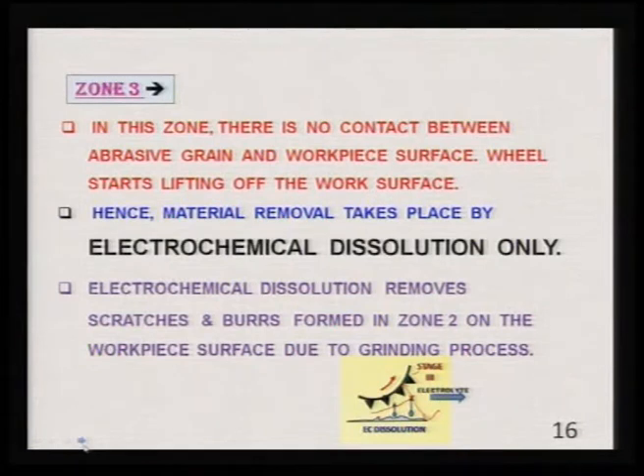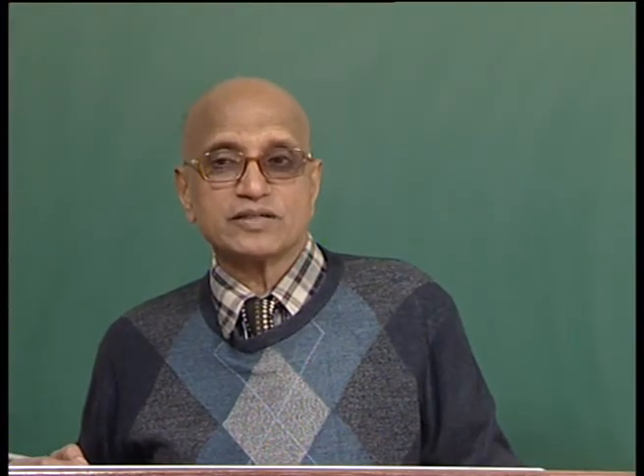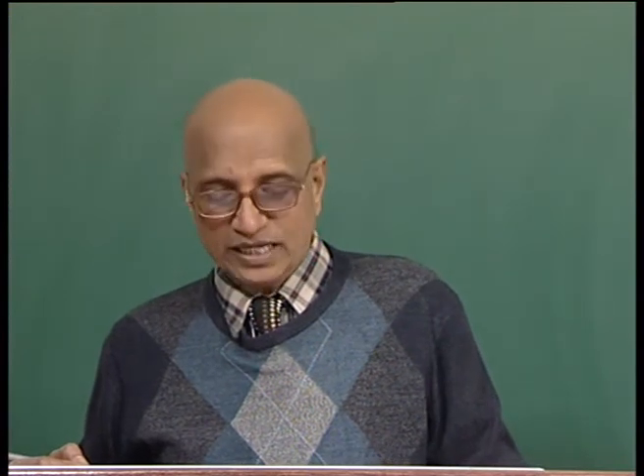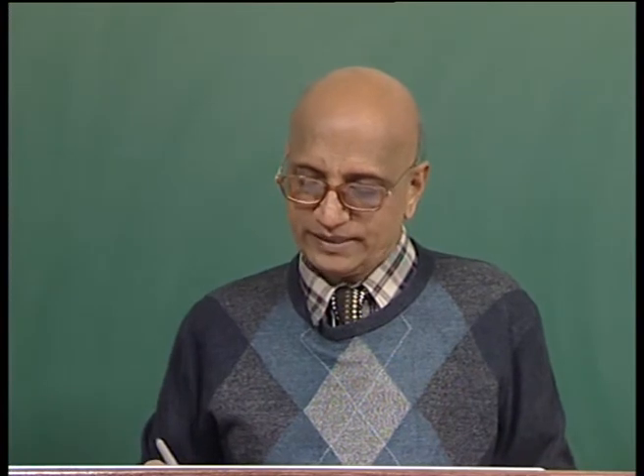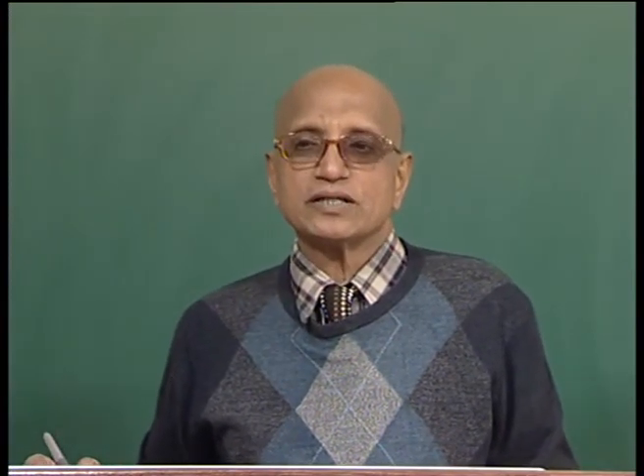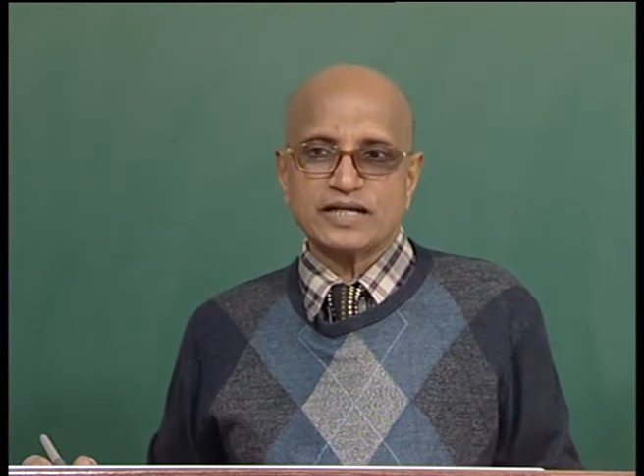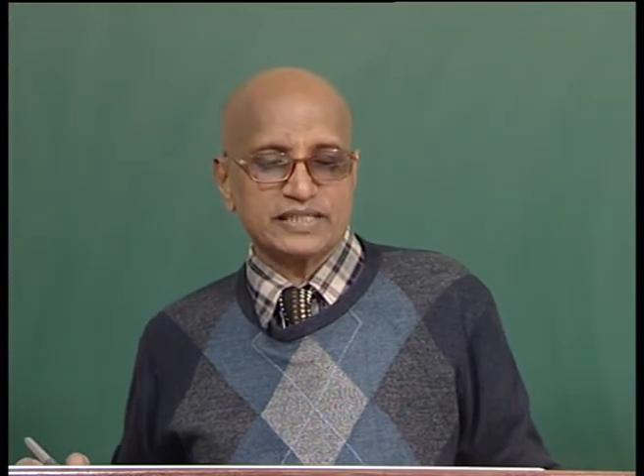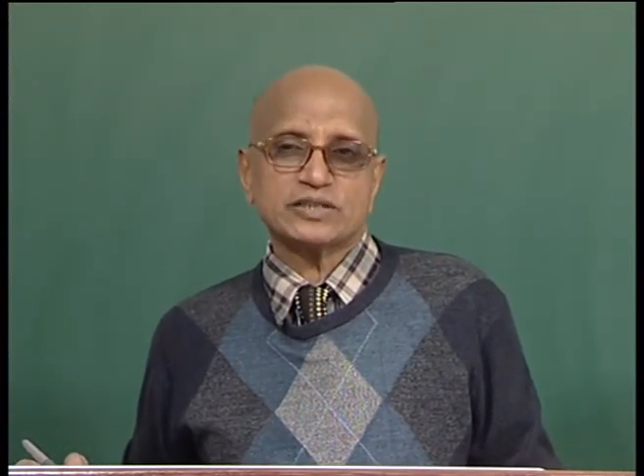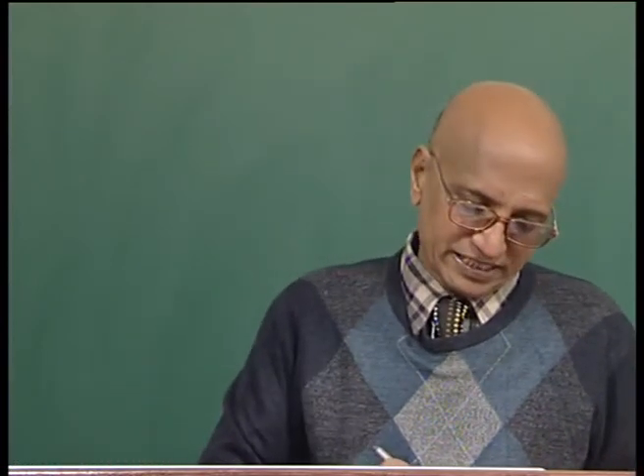Electrochemical dissolution removes scratches and burrs formed in zone 2 on the workpiece surface due to grinding process. We have seen in the last but one slide that material was removed by abrasive particle from the workpiece surface, and that was a grinding process, and due to grinding burrs and scratches are formed on the workpiece surface, and these scratches and burrs are removed in zone 3, that is shown over here. So, you get burr free and scratch free surface after zone 3 in case of electrochemical grinding. So, this is an additional advantage of electrochemical grinding over conventional grinding process.